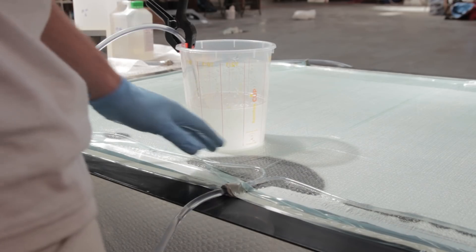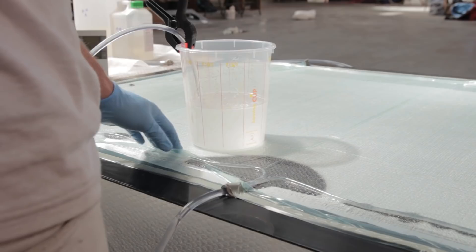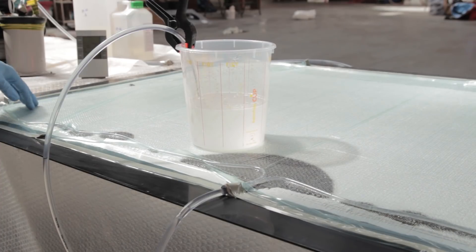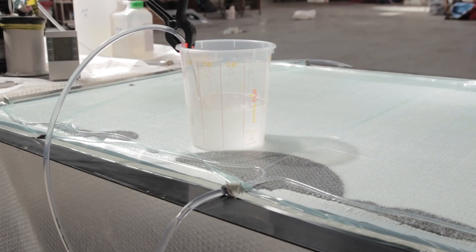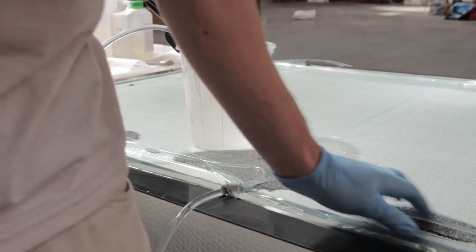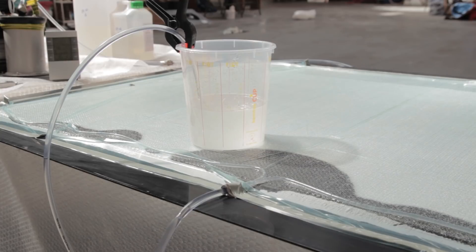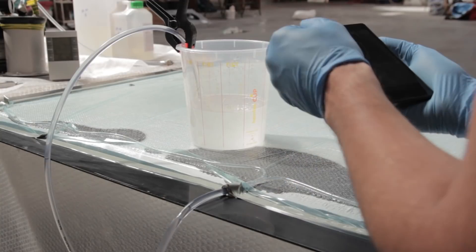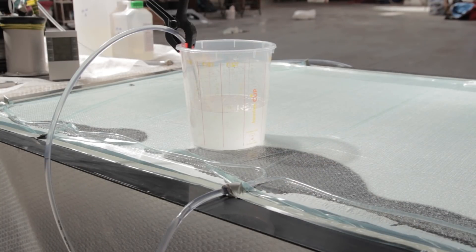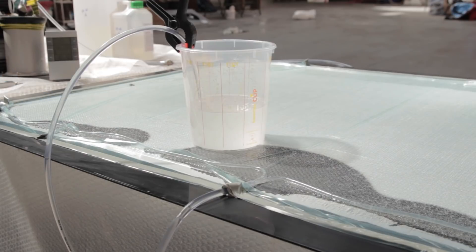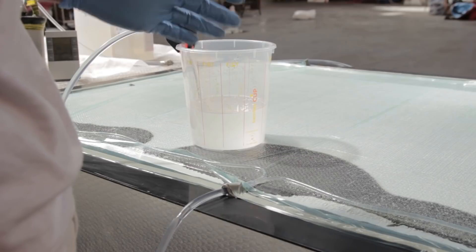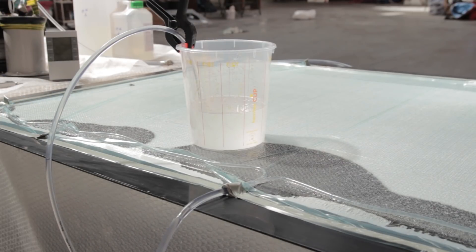I'll share more about the findings and what went wrong. First thing you can see is that the resin is not clear. You only have a pot life of around 25 minutes. For me, that's a big problem or a no-go on big plates, but I decided to try it because I had good faith in it. I even did a live stream on my Facebook going through this process. But the biggest problem is the pot life. If you're going through a big infusion and you only get 25 minutes for mixture, degassing, and then infusing, that can cause problems of the resin kicking too fast into the cup or even into the laminate.